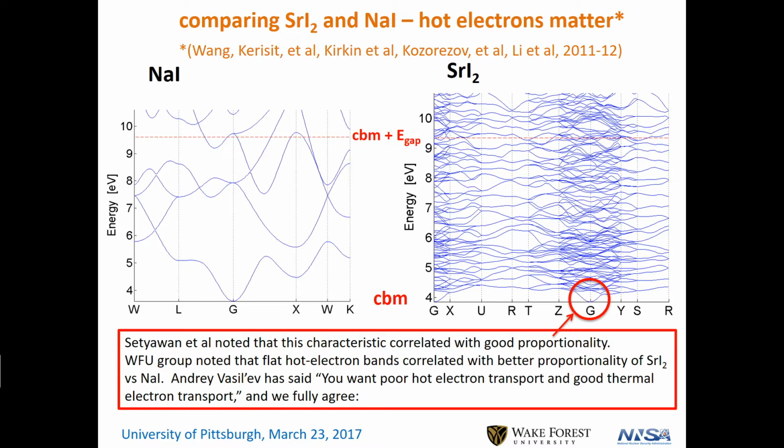How come? So I had a student, a theoretical student, calculating the group velocity. This is a 2-atom unit cell, so it's got very simple bands. This is a 24-atom unit cell, a large unit cell, with very complicated dispersion bands, but mostly very flat dispersion bands. So the group velocity is very low in this material.